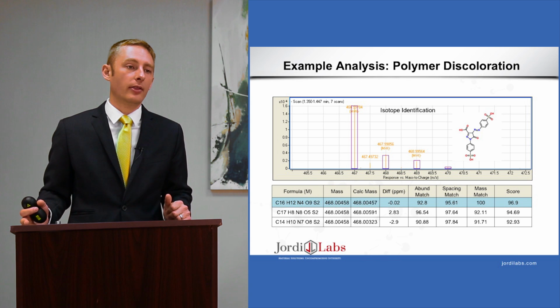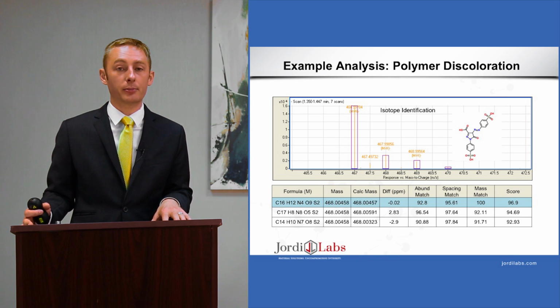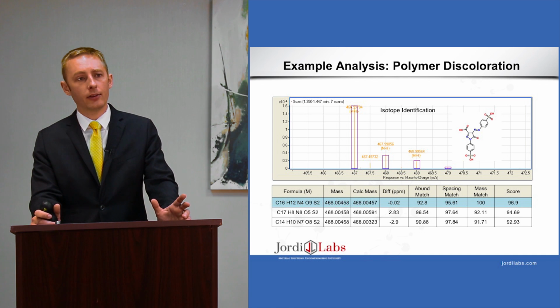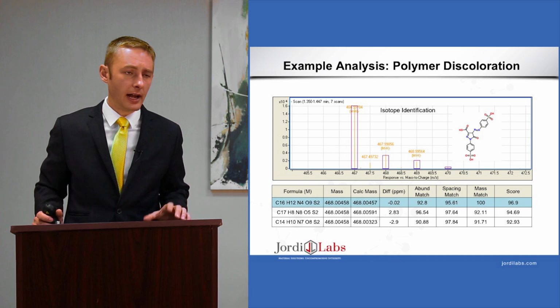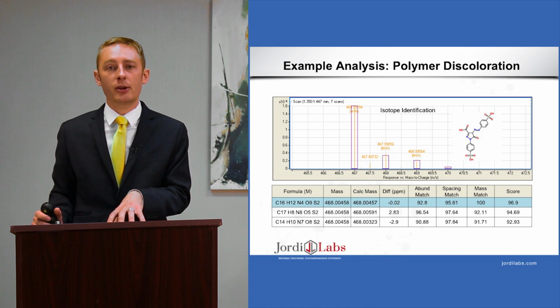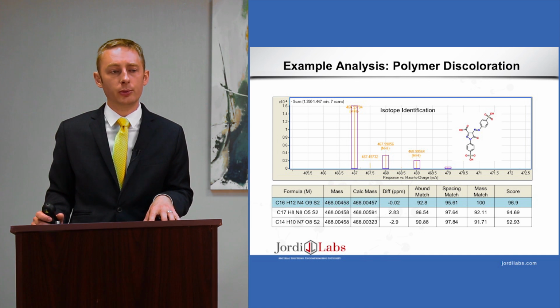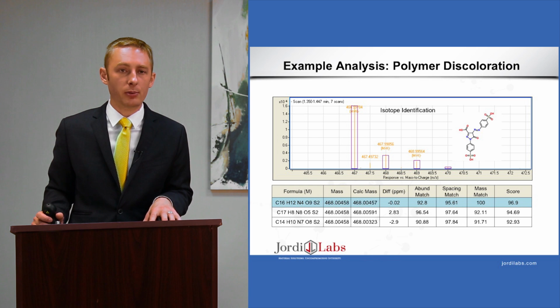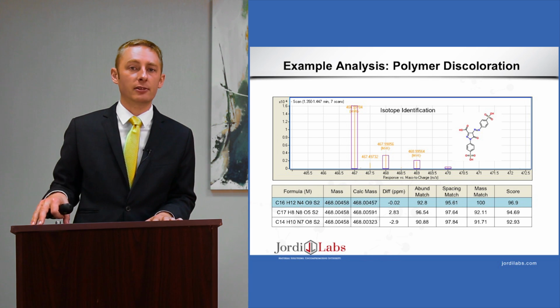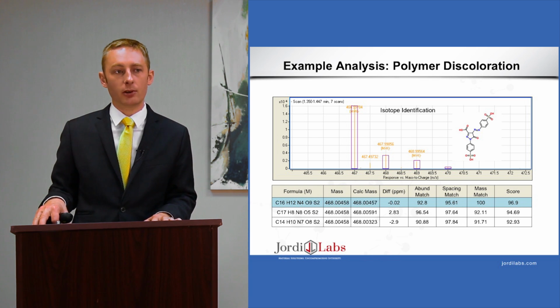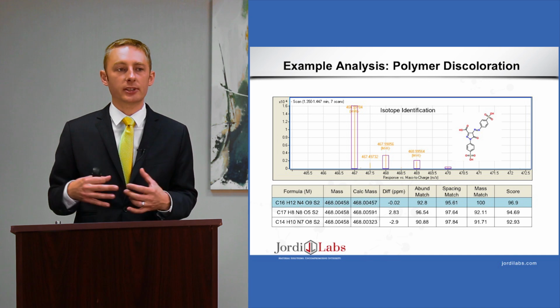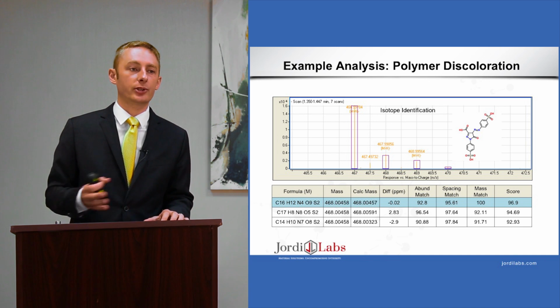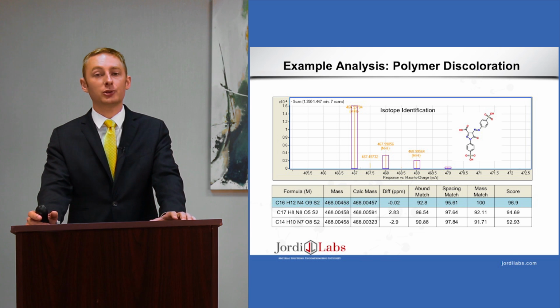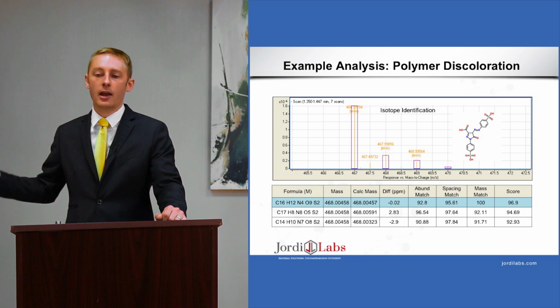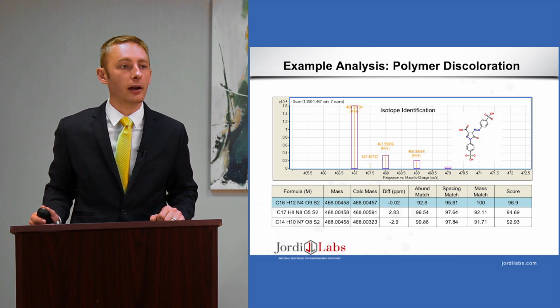An algorithm that determines the molecular formula for that particular mass. And in this particular case, we're able to identify the component that's present on the screen right there, and we're able to provide that information to the client, and they're able to look at what they were doing to formulate this particular polymer system, and they were able to identify two different components that were cross-linking in their polymer system over time when exposed to UV light. And they were able to eliminate that from their polymer system and move forward with production for this syringe.